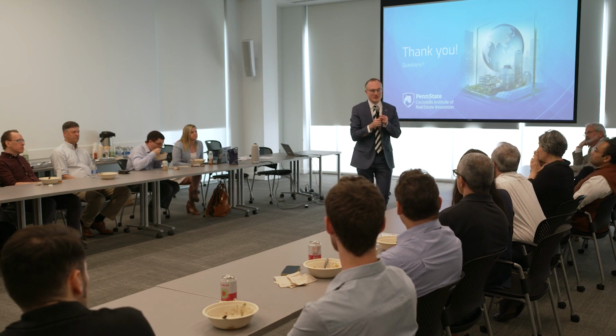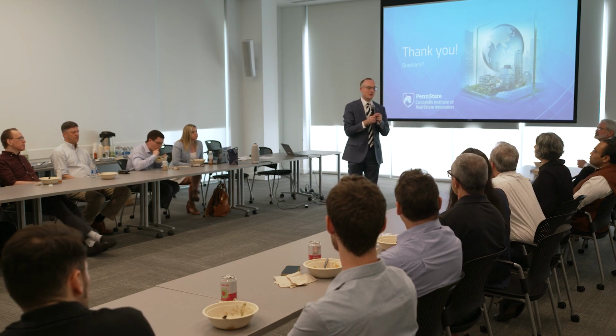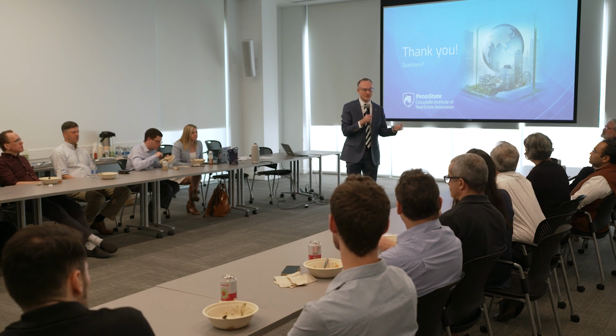Great question. My expectation is that the performance should be very similar to the performance with soda lime silicate. And the reason is that the thermal conductivity of glass really doesn't change all that much from glass to glass. The reason is because of the non-crystalline structure of glass. Materials that have really good thermal conductivity are things like diamond or other perfect crystals that are able to propagate the waves without having any scattering. With a glassy material, it gets scattered every step of the way.